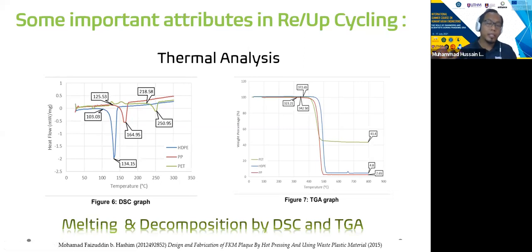Another aspect of thermal analysis is the degradation or decomposition of the materials. If you want to know the decomposition of the material and what the residue is as a result of burning out these materials, then TGA, thermogravimetric analysis, can be used. If you refer to this one, it can be found that the blue and the red, representing the HDPE and PP, decompose almost completely. The remaining is in the form of ash, less than 5%. However, for the PET, the remaining compound is more than 40%. So this is one of the critical issues for PET from the standpoint of thermal behavior.